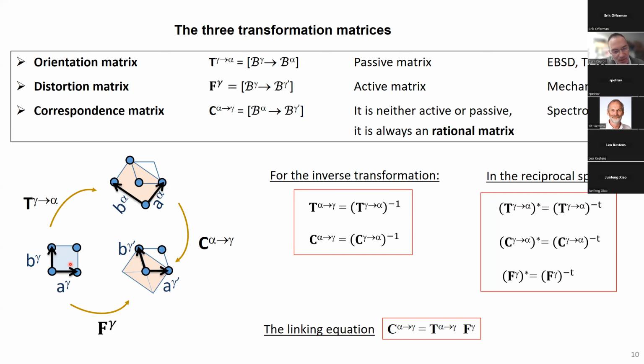Now, if I know that this transformation is displacive, I can look at how I can go from here to here. I say, look, if I take this square and I slightly distort this square to form this rhombus here, then this rhombus is the same as here, and I will form this centered rectangular phase. So this distortion is called the lattice distortion, and I call it the distortion matrix. I go from b gamma, that is my parent phase, to b gamma prime. Prime means distortion.